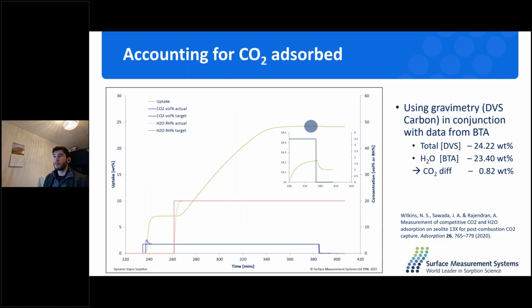So from the breakthrough analysis, the total uptake of water in these conditions, we are very sure, is around 23.4 weight%. One thing we can do is take the difference between these two and obtain an actual amount of CO2 adsorbed, which is around 0.82% by weight. If you want to learn more about this approach to determining uptakes, there is a very good paper from the University of Alberta from Arvind Rajendran's group, where they also measure CO2 and water on zeolite 13X. But the point to highlight is that there is no one method that can get you what you want.